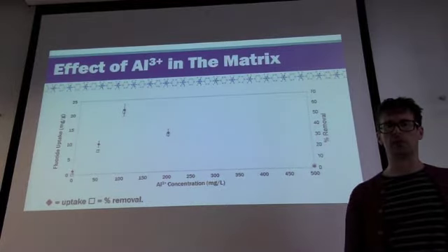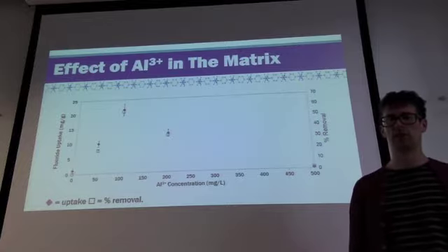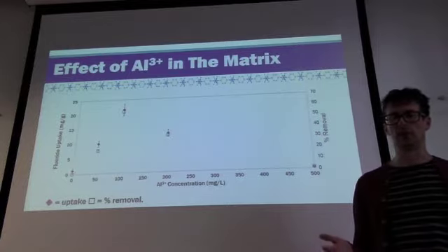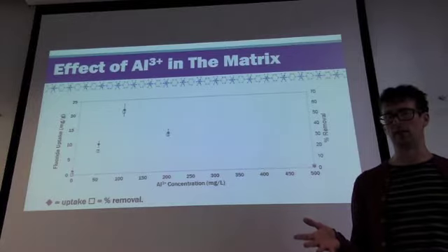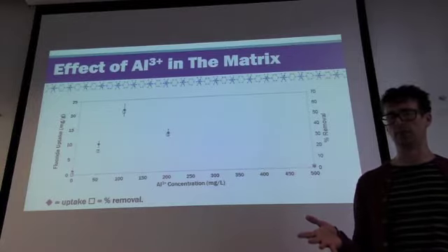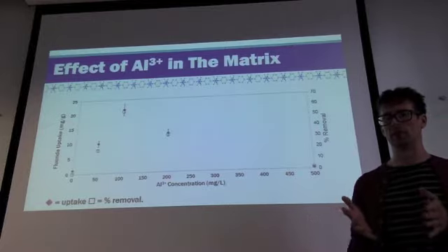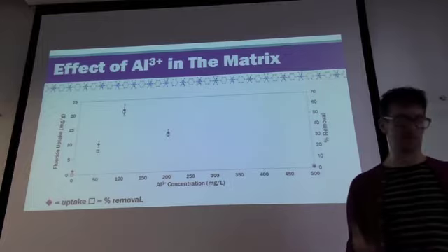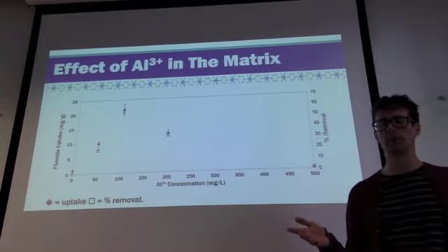So in subsequent studies, we began to vary the concentrations of the different components in the emulant leachate matrix. And by doing this, it was revealed that it was actually mainly the dissolved aluminium in the system, which, when present at a certain molar ratio, aluminium to fluoride, appeared to have this strongly activating effect on the resin's performance, which is what this graph shows here.